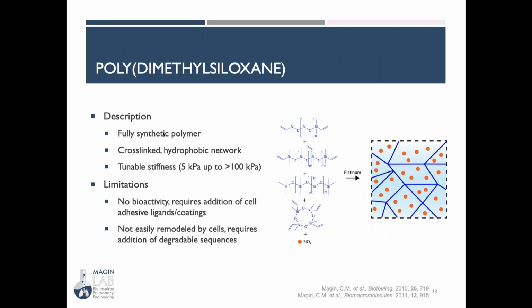All right, silicones. I spent most of my early career studying anti-fouling, and we used silicones to keep things from sticking to the sides of ships. So this is a fully synthetic cross-linked polymer. It makes a hydrophobic network. It's often filled with silica and platinum catalyzed. This is, again, a tunable stiffness substrate. You can create silicones that have a modulus of 5 to over 100 kilopascals, and it has the same types of limitations as the previous materials that I mentioned before.